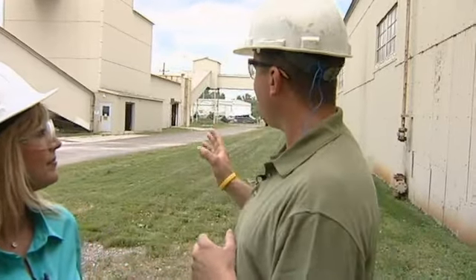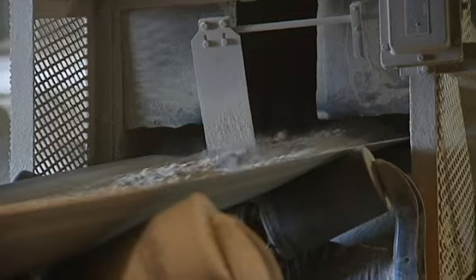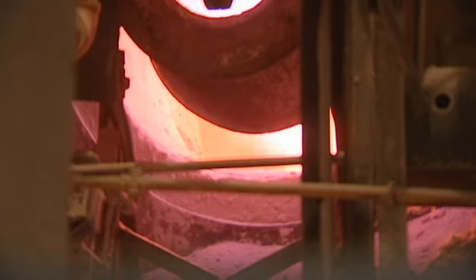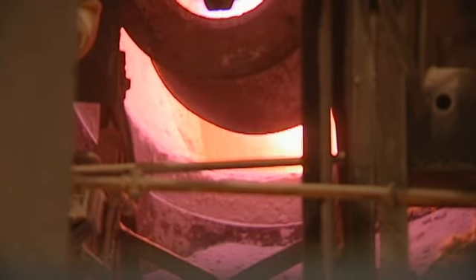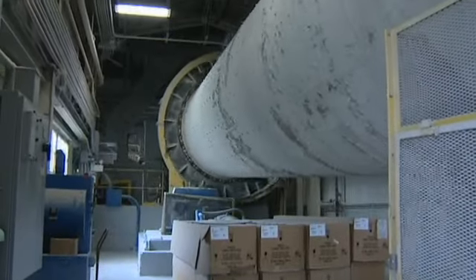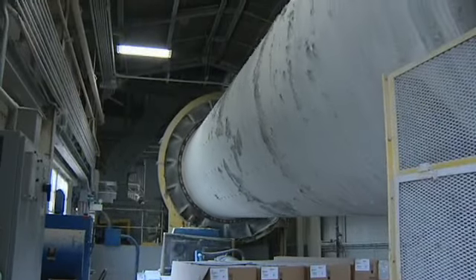Okay, the mixture that the bulldozer just mixed, the synthetic and natural rock, is going into this building. From here, we're going to screen it. We're going to run it through an impactor for the coarse particles to get down to size. Then we're also drying it. We're shooting it through a flame to dry off all the free water, which isn't part of the chemically combined gypsum water. It's rain, snow, sleet, all that other stuff.